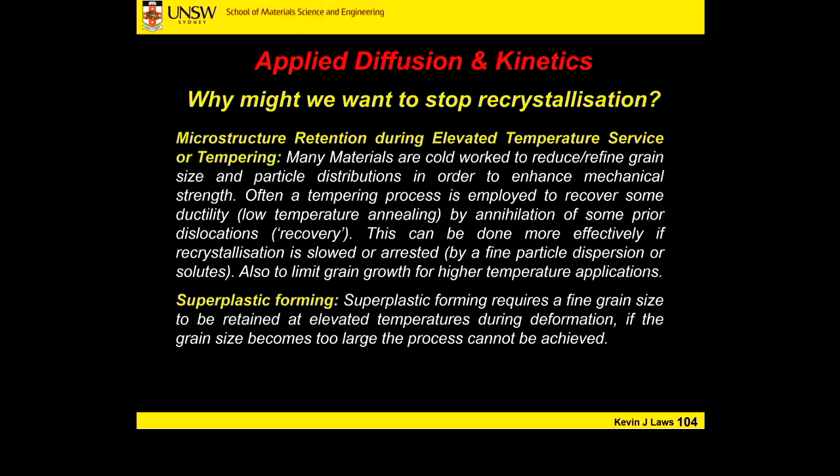With recrystallization and grain growth, grains grow big, our grain boundary surface area becomes smaller overall, compared to a very fine grain size, so we can no longer superplastically deform the material. And we can't do this forming process.